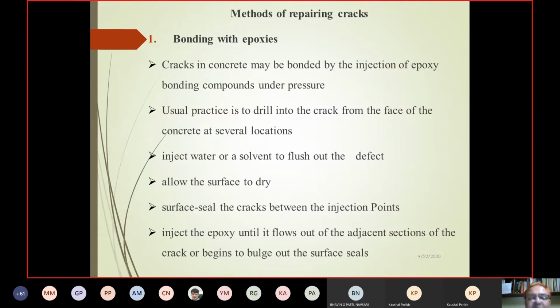Then bonding with epoxies. We can use epoxies to inject into the concrete. Epoxy should be used for structural repair, not for water leaking. Epoxy bonds under pressure. The injection routing is there. If we are using cementitious material, then 10 psi pressure should be there. If we are using epoxy, then 90 to 100 psi pressure should be there in injection.